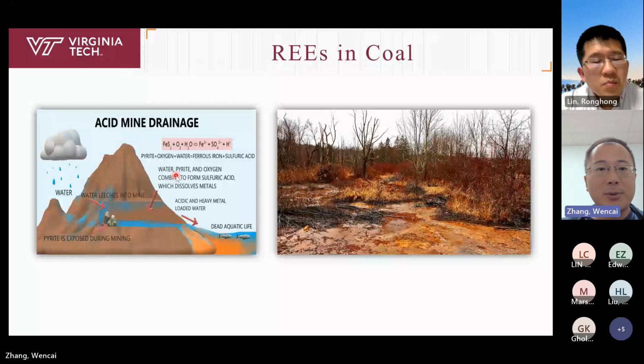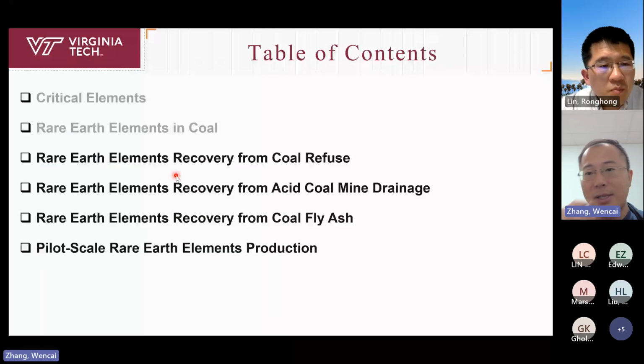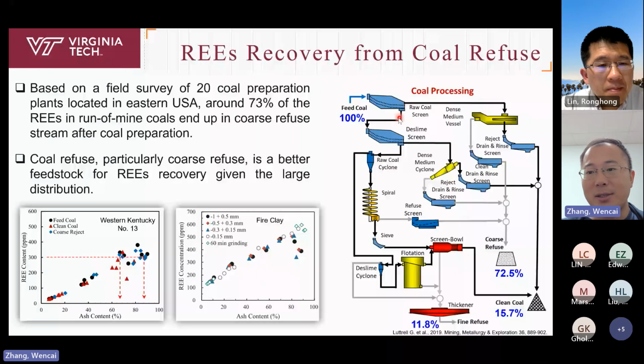So now let's talk about the rare earth recovery from coal. As I mentioned, after coal preparation, it generates different products. For example, you have coal refuse, you have clean coal, you have fine refuse. There was a survey based on around 20 coal preparation plants in the eastern US. They collected samples from each stream in the coal preparation plants, and they found that on average, around 72.5% of rare earths in the run-of-mine coal goes to the coal refuse.